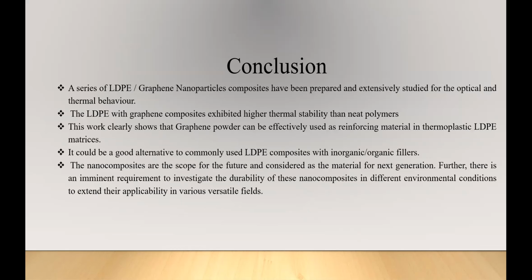To conclude, a series of LDPE graphene nanoparticle composites have been prepared and extensively studied for their optical and thermal behavior. The LDPE with graphene composite exhibited higher thermal stability than neat polymer. This work clearly shows graphene powder can be effectively used as reinforcing material in thermoplastic LDPE matrices. It's a good alternative to commonly used LDPE composites with inorganic and organic fillers.